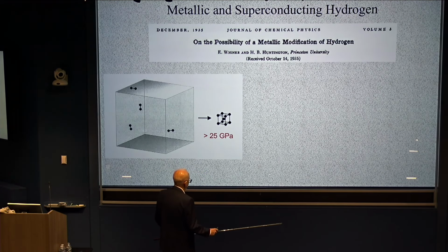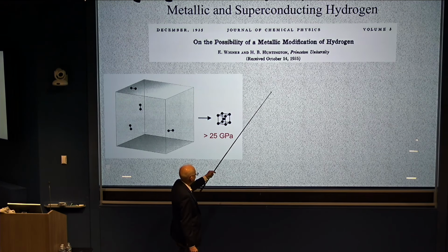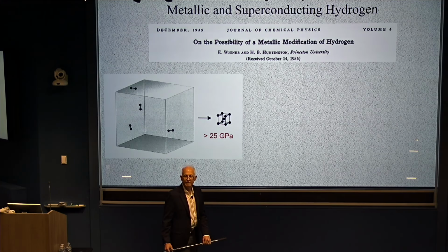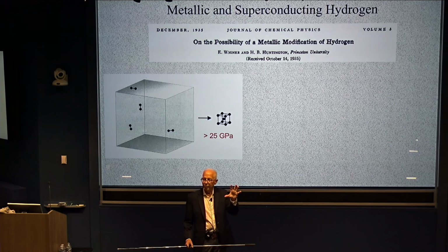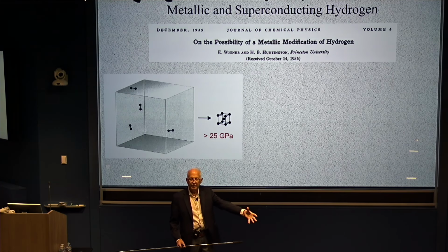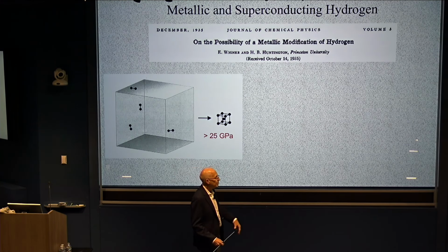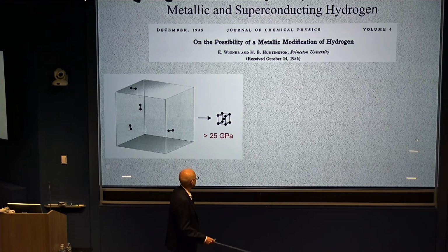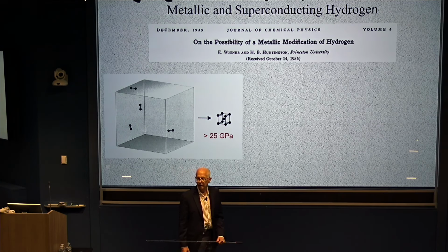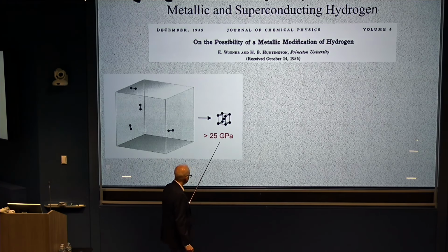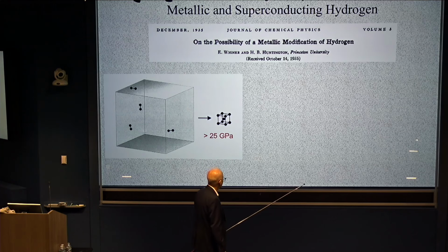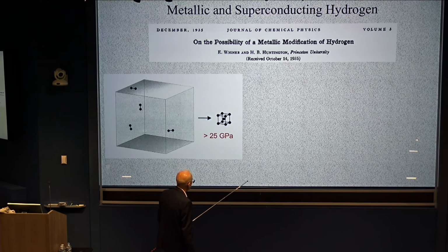This really began with the paper that I mentioned earlier, the prediction by Wigner and Huntington that when you compress hydrogen, it must ultimately transform into some non-molecular atomic state. At the time, they suggested this would happen above 250 kilobars, 25 GPa. People sometimes say they predicted it at 25. It's actually, they were clever in saying it's going to be above 25 GPa. So they are right. It is above 25 GPa.